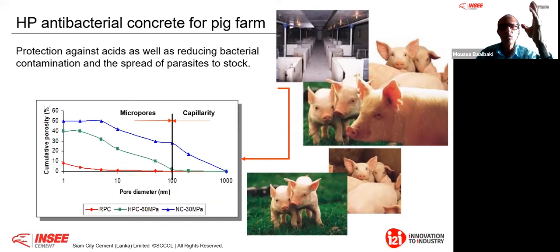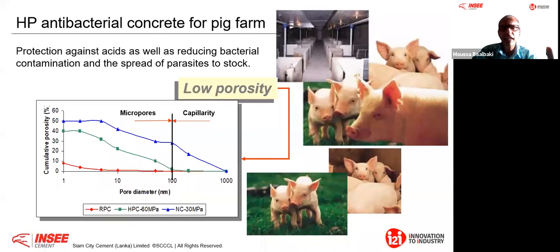The way we did it is we designed with Portland composite cement where we have transformed the capillarity to mesopores. Therefore, when you do, for example, what we call the gas permeability, you look and you realize that your capillaries are below 100 nanometer. Above 100 nanometer, this has a big impact on the compressive strength. That is why you have to reduce your water cement ratio. And below 100 nanometer, this is the durability. Shrinkage, volumetric change, or percolated gas that can come in, or aggressive elements. That is why you need to go more to micropores. Okay, just to give you here, the indicator we were looking for is low porosity. Nothing to do with the compressive strength.